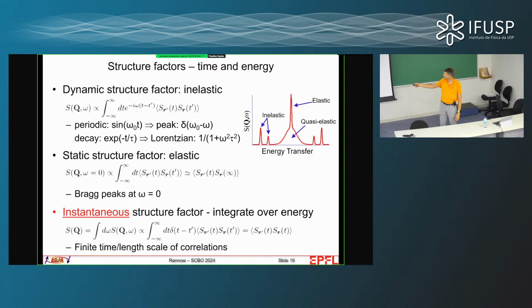If I had something that decays exponentially with time, so a damped oscillation, I would get, instead of a sharp delta function peak, a Lorentzian peak with a certain width. Now there's a couple of special cases. If I measure explicitly at zero energy transfer, I can inspect my Fourier transform and see that that corresponds to something which is independent of time. So I need to have something static, like static order. So if all the spins, all the magnetic moments in my sample order, for instance into a ferromagnet, then I would get a signal which is the same as the Bragg peaks that you see when you do X-ray diffraction of a crystal structure.